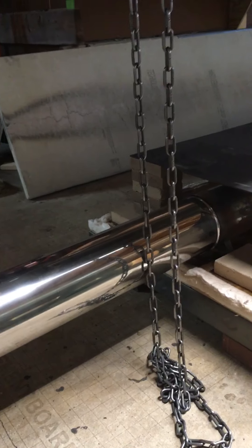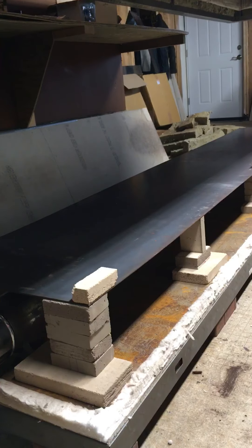We're going to try to blow more hot air down the flame tube rather than the flame itself — we're trying to get air down there, not flame. We had flame there and what happened was it actually heated the glass too hot and distorted it. It must have been over 1300 degrees at that point.